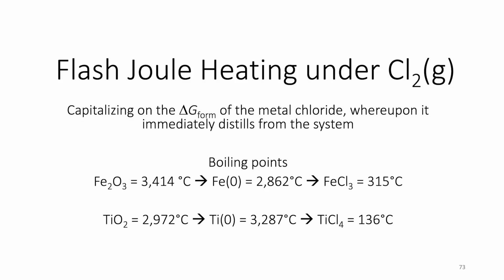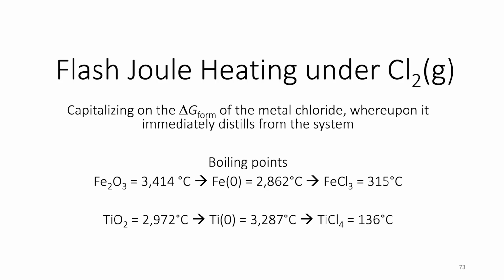And so if you look at boiling points, iron oxide is 3,400 degrees C. Iron metal is 2,800 degrees C. Iron chloride is 315. If you can make the chlorides, you can distill very easily. Titanium oxide, 2,900. Titanium metal, 3,200.